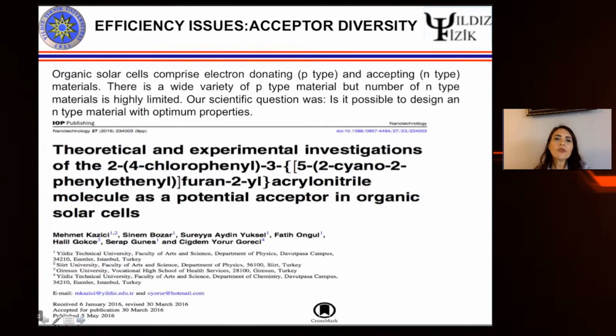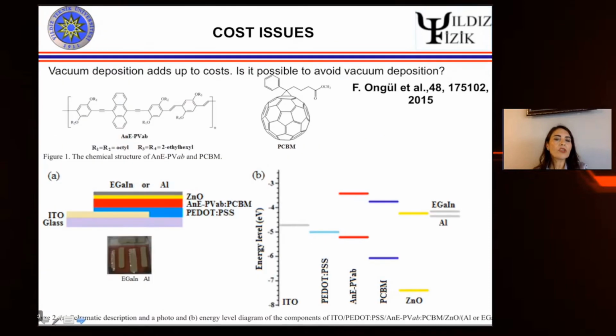For the efficiency issues, this is one of the works from my group. Mehmet Kazici was my PhD student, and at that time, in organic solar cells, there were many electron donating, that means p-type materials, but electron accepting materials were limited. So our scientific question was, is it possible to design an n-type material with optimum properties? Mehmet was doing the theoretical measurements, and Çiğdem Yürür-Göreci was the one who synthesized these materials for us. And we really achieved high open circuit voltages.